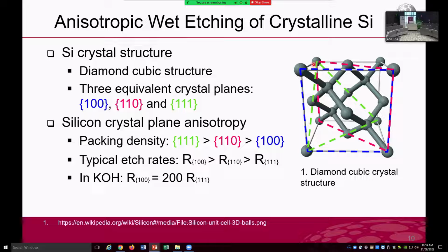If the etchant is correctly selected, then the etchant will selectively attack certain planes with minimum damage on other planes. That's the underlying mechanism of achieving anisotropic etch profiles on a crystalline silicon structure. For example, the 111 plane shows the biggest atomic packing density. That means it shows the lowest etch rate in certain etchants. So for example, in potassium hydroxide solution, the etch rate of the 100 plane is 200 times higher than the etch rate of the 111 plane.